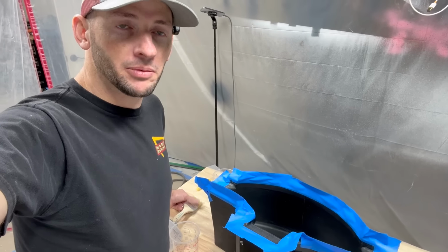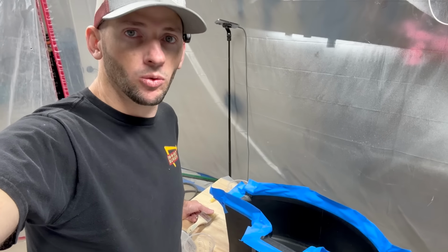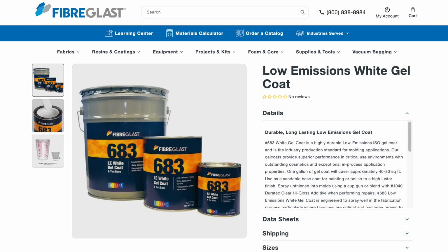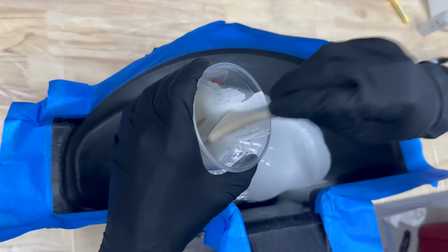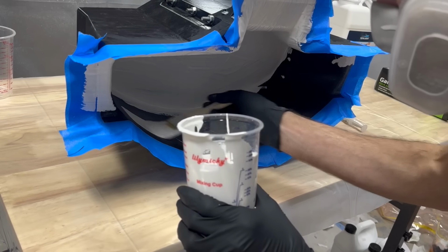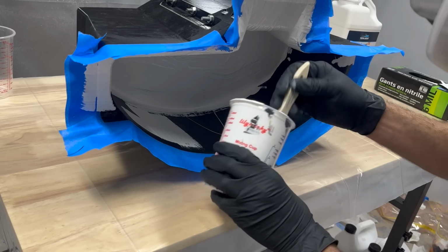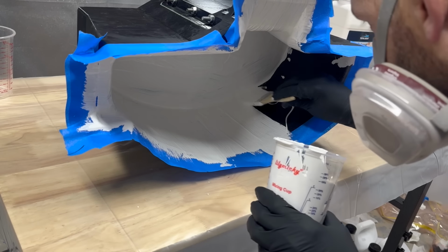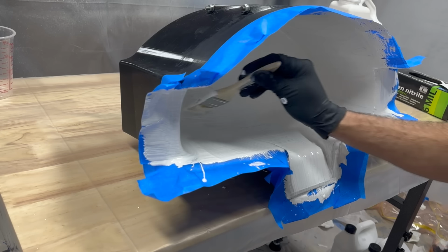For the gel coat, I'm going to be using regular gel coat without wax. This is not tooling gel coat. I'm going to mix it and kick it off at about 1.75%, I think. It's about 70 degrees down in the basement. I want it to kick relatively fast, but I don't want it to get too hot for this PETG mold.